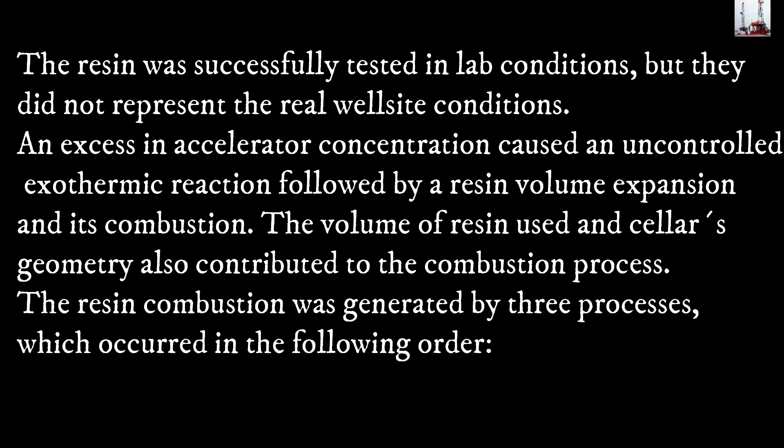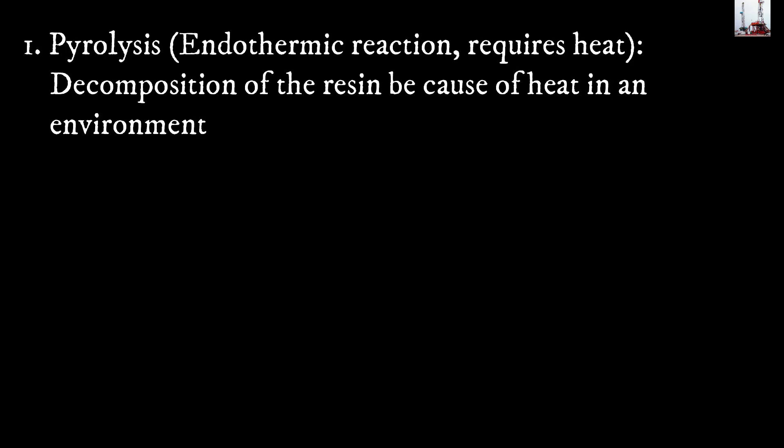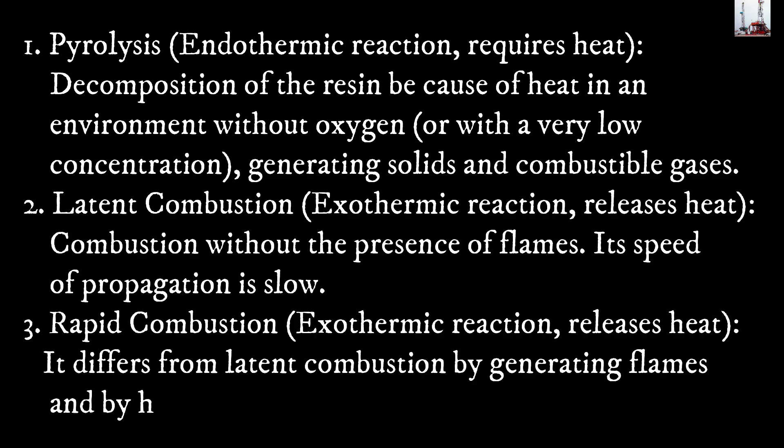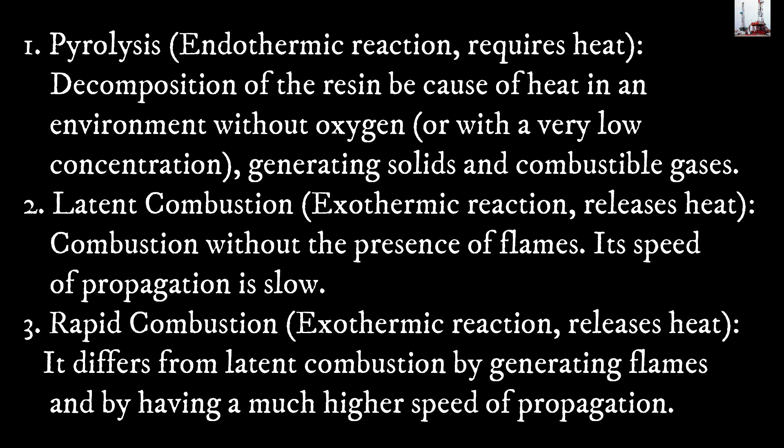The resin combustion was generated by three processes which occurred in the following order. 1. Pyrolysis: thermal decomposition of the resin due to heat in an environment without oxygen, or with very low oxygen concentration, generating solids and combustible gases. 2. Latent combustion: an exothermic reaction that releases heat without the presence of flames.